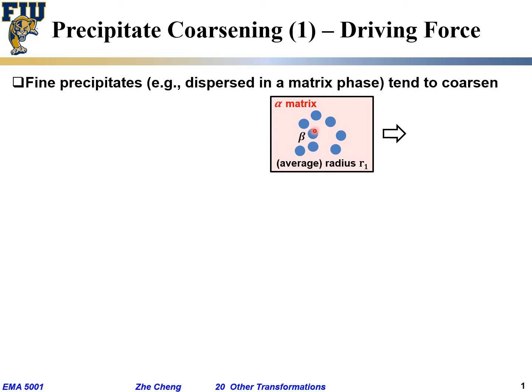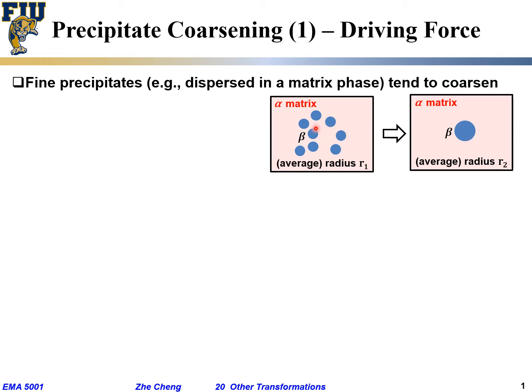On the other hand, if we are not careful—if we use the material above a certain critical temperature or leave it in the furnace too long—over time the number of fine precipitates becomes smaller and smaller, their density decreases, and each individual precipitate becomes much larger with an average radius r2. It is still a two-phase system of alpha and beta, except the secondary phase is now distributed differently, with individual particles getting larger. This is what people call coarsening.